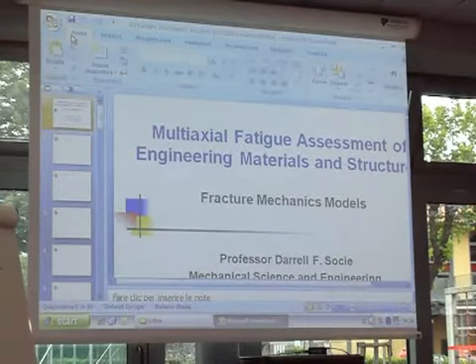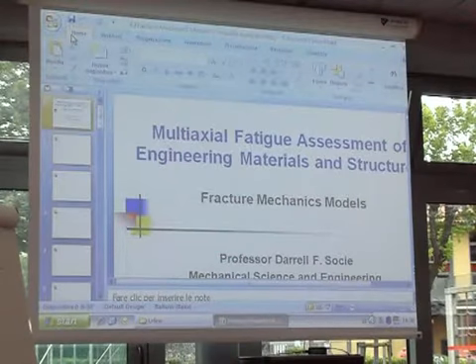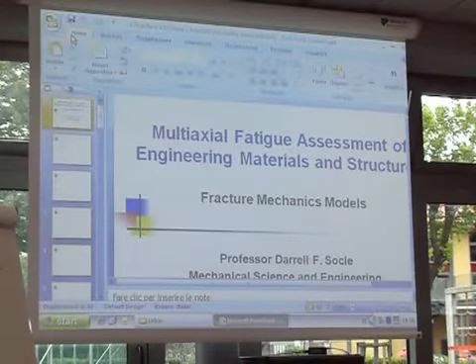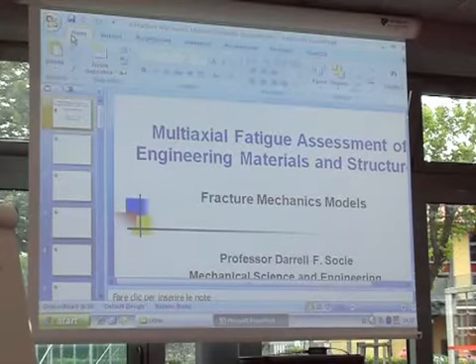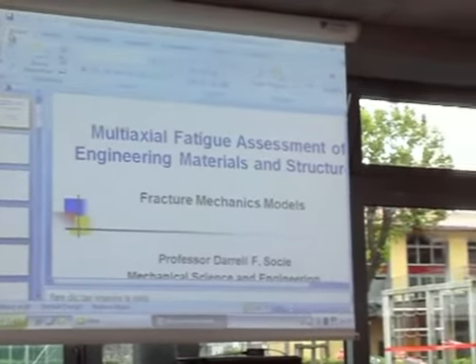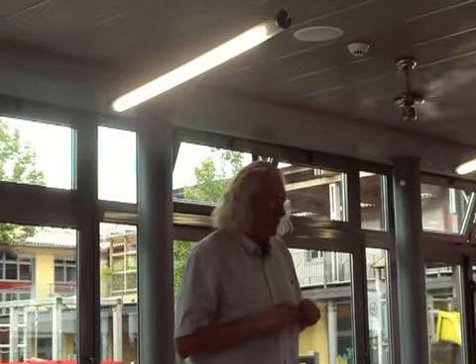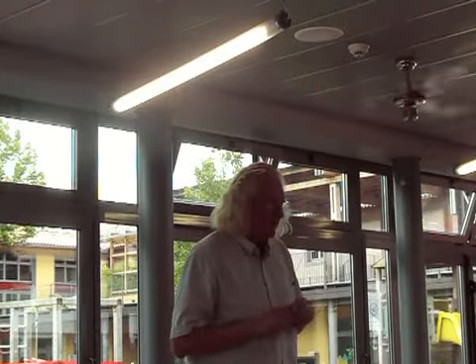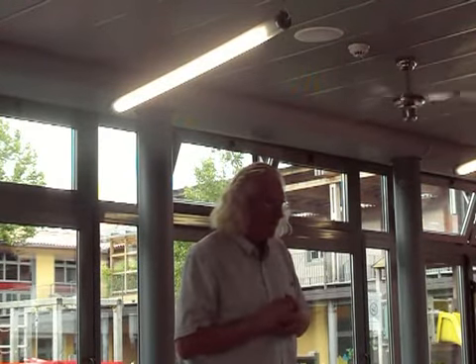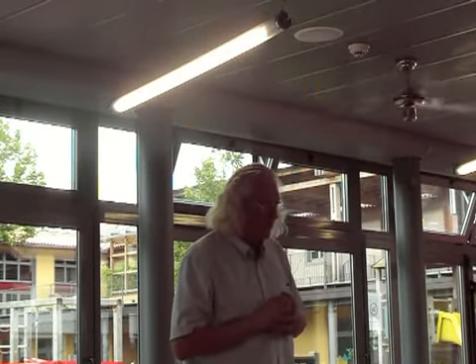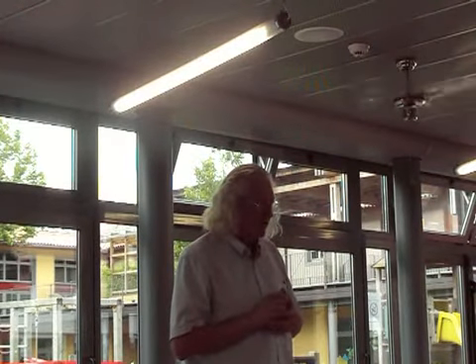A crack will grow along the interface. Because I'm working on mixed mode, with the crack growing in foam core, or these very low density materials. So do you think that's the same? Because actually, I'm making cracks grow quite long, but I don't know if they're growing under a single mode. But maybe if you say it's a fake single mode, so that's mode 1 or mode 2. I think that's what happens. The crack tries to grow with one mode dominant. Yes, I think there's a dominant one. Sure. Yes, there is.